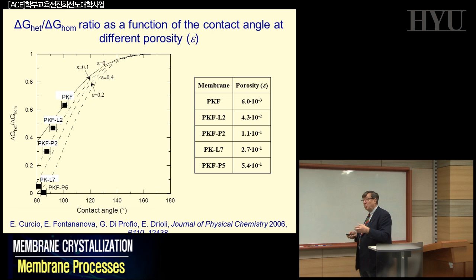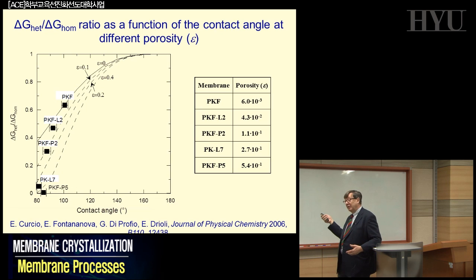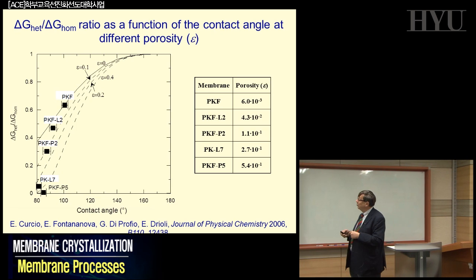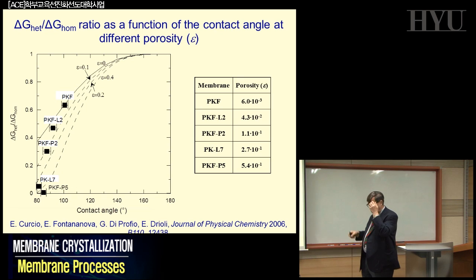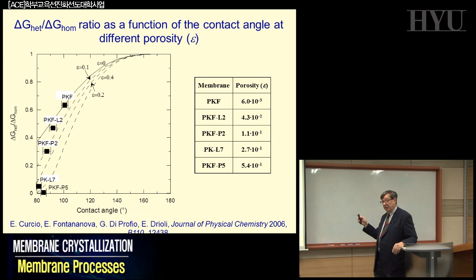So all the parameters which characterize a membrane are quite important, not only for helping the evaporation, but for promoting this delta G heterogeneous, delta G homogeneous, and that means kinetic phenomena. Kinetic phenomena is not just speed in crystal formation, it can be much more than this, because we will see very soon that when you want to study, and we mentioned before, one of the dreams is how to control a polymorph at the end, how to produce an enantiomeric form with a very high level of purity. One way to solve this problem is to have control in the metastable phase of the supersaturated solution, to control the kinetic of the crystals of some intermediate products. That's the way to change completely the final product you can obtain, and we will see the situation.